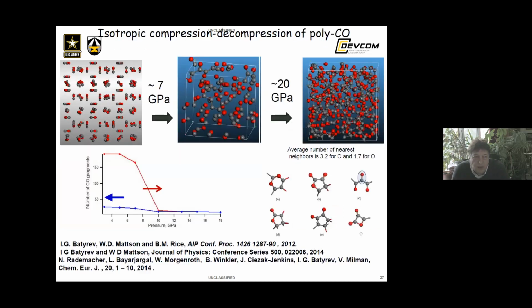If we start from the molecular delta phase of polyCO, 128 atoms, 64 CO molecules, and simulate isotropic compression, then at 7 GPa one may see the beginning of polymerization. And at 20 GPa, all intact molecules are included in a random covalent network of polyCO. It consists of a network of rings and penetrating and bending chains.